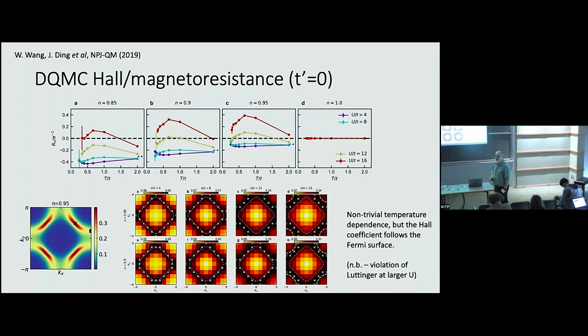And then if you continue your linear temperature dependence, it seems to intersect the vertical axis at a finite value. So there is no disorder, right? There's no disorder in your simulations. Yes. Is it an artifact of the sign problem? No, it's an artifact of analytic continuation. Because unfortunately, once that Drude peak gets to be smaller than temperature, kBT or so, then you have the most terrible thing to do analytic continuation on, which is a sharp peak, a broad continuum, and another hump that sits out there. That's really bad. Okay, I'll be corrected.